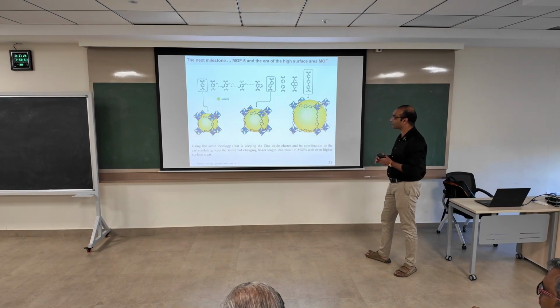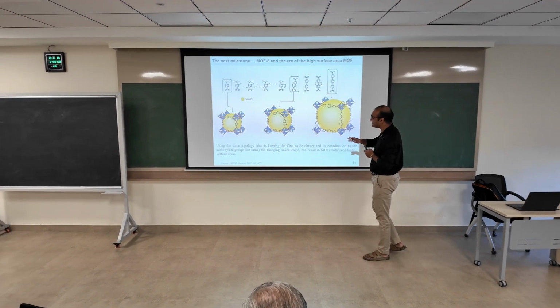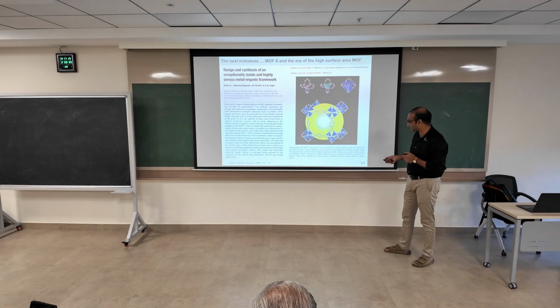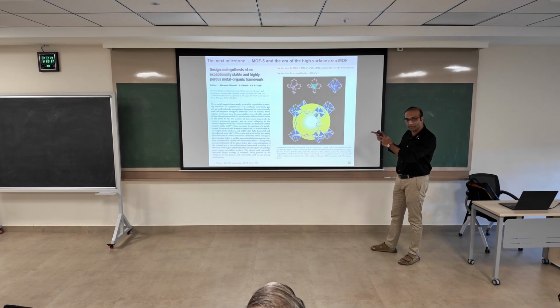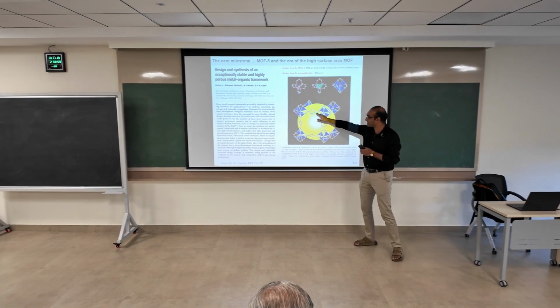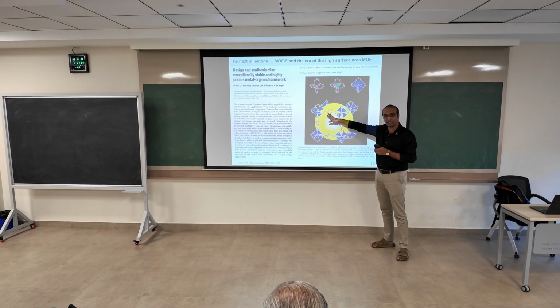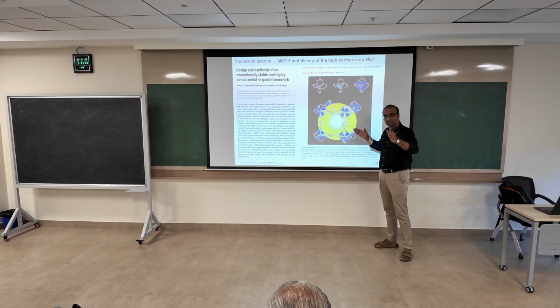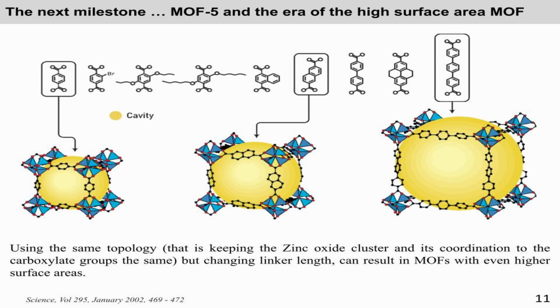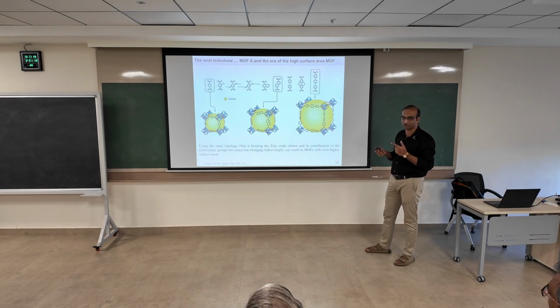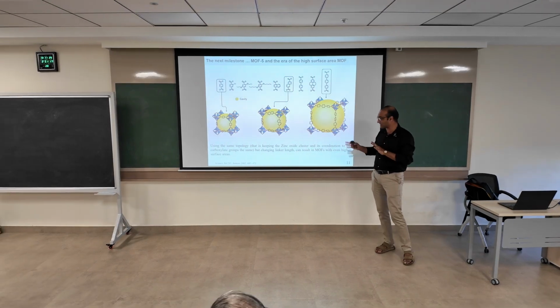Yeah, so one more thing: what you can't do with zeolites is, see here there was a certain space, right? You had like 18.5 angstrom. If you wanted to make this space bigger, you can make this a double linker, like a bipyridyl, and increase the length of the chain of the linker. When you increase the chain of the linker, you can make more and more space. The voids become larger and larger, and then you can have more and more space to occupy different types of host-guest interactions. Okay, so again, Yaghi did a lot of work to show this, and it was possible.